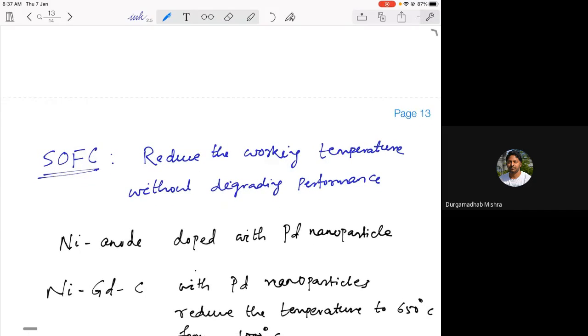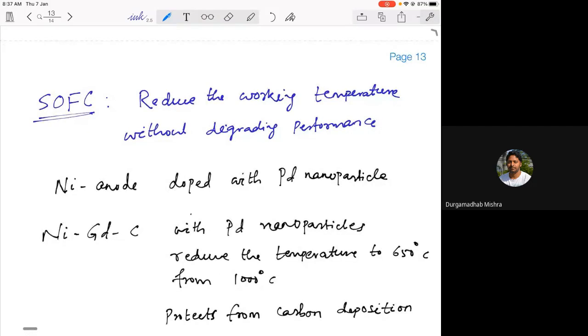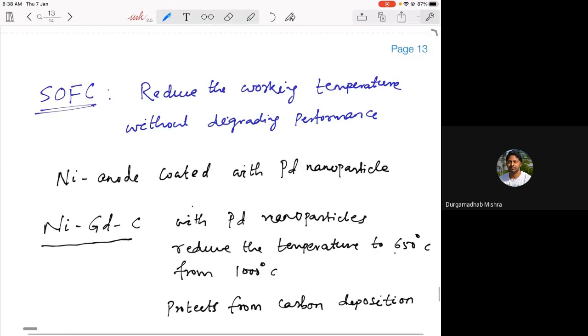There are various ways that can be done. For example, I should not say doping here, but rather coating. A palladium nanoparticle is coated on a nickel anode, or sometimes a nickel gadolinium and carbon-based alloy is used instead of pure nickel, because of the high temperature applications. With palladium nanoparticles, it has been observed that this solid oxide fuel cell can work even at 650 degrees Celsius instead of going to 1000 degrees Celsius. So you can operate the fuel cell at 650 degrees Celsius.